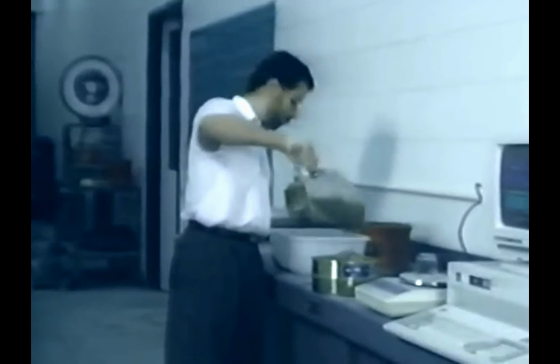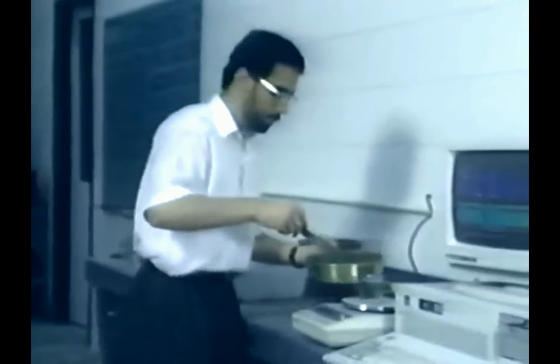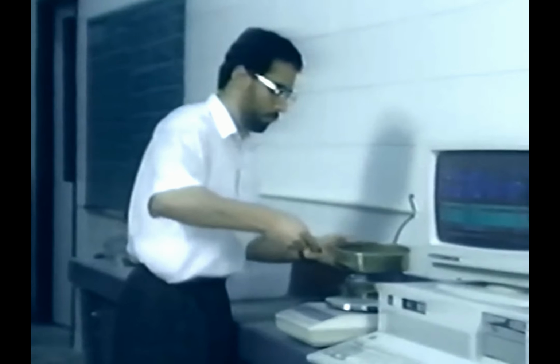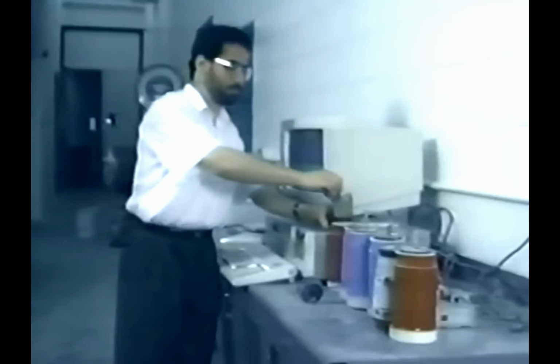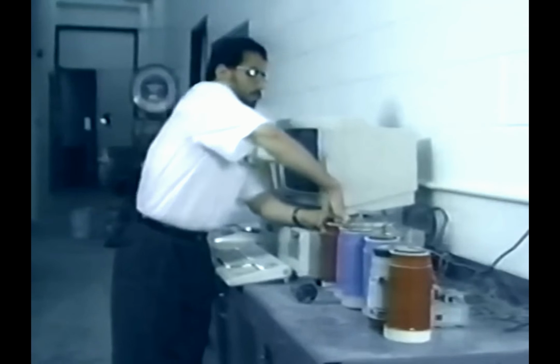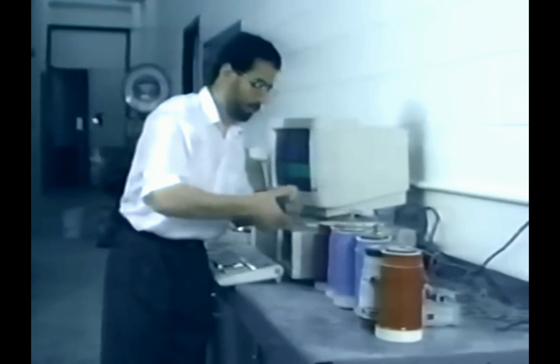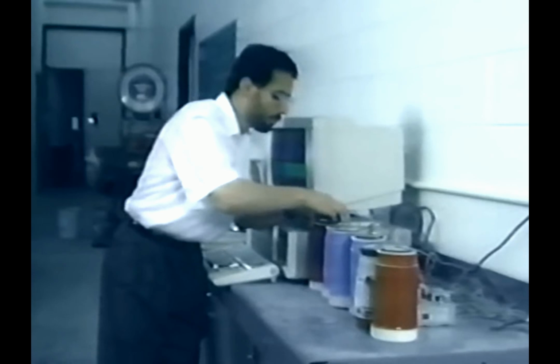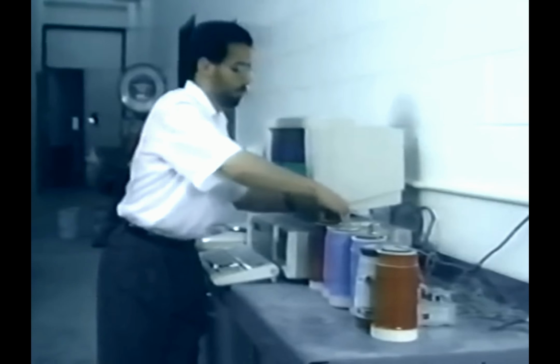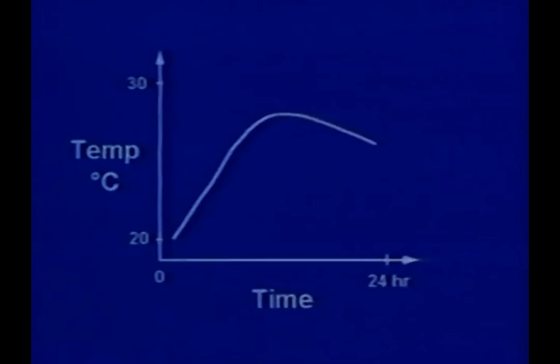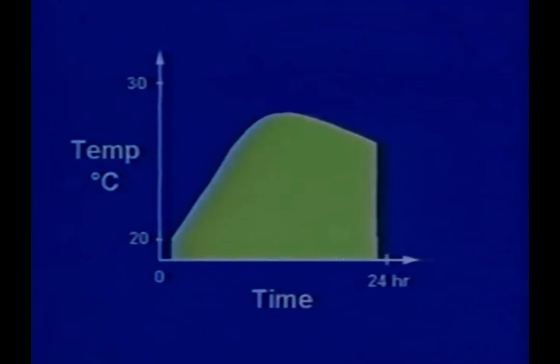Hydration is an exothermic process which generates heat through chemical reactions. The process of hydration can be easily followed by monitoring the production of heat that accompanies the reactions. This is done by sieving mortar from a batch of concrete and weighing it into a bottle which is placed into an insulated container. A thermistor is then embedded into the fresh mortar. The output of the thermistor can be recorded by a computer. The results of this experiment can be plotted as a curve of temperature versus time. The area under the major peak can be related to early strength development.